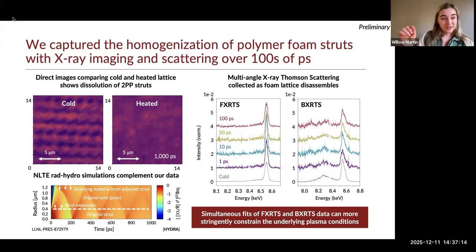You'll see, if you track the electron and ion temperature as a function of time in a solid density sample, they would just equilibrate quickly and then track with one another. But what's interesting about these foams is that when you have your strut expanding and then colliding with neighboring foams, you can actually drive up the ion temperature beyond the electron temperature. So you kind of overshoot that equilibrium point, and then eventually, slowly, once you're homogenized, come back down to an equilibrium. Jose Milovich has some really interesting simulation work on this too, for subcritical density foams.